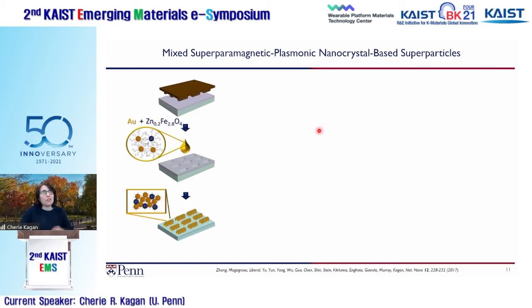Again, I'll add a little bit of complexity, building on the same kinds of ideas of using imprint lithography. We also combine, for example, gold particles with zinc ferrite. Now, zinc ferrite is a magnetic material. At the size that we use them, they're superparamagnetic. So they're not yet big enough to be ferromagnetic, but it means that they have a high magnetic saturation but no coercivity. I'll show you that in a second.